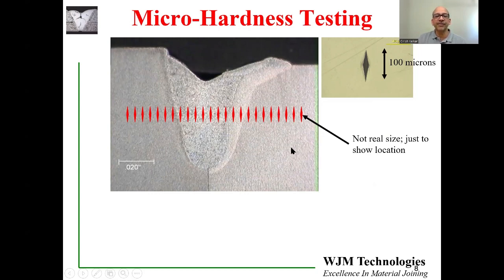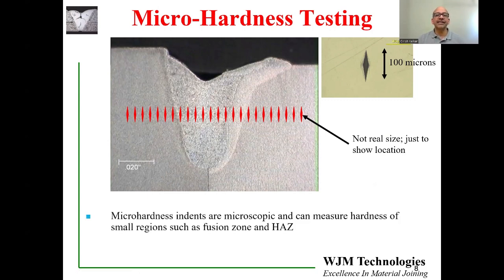So a combination of metallurgical analysis and micro-hardness testing gives a fairly complete picture of the expected behavior of the weld. There are other techniques that can be used, such as SEM and EDAX, to identify different elemental distributions in the weld, but that is not often necessary. So I would say in the majority of the cases, a good cross-section and micro-hardness testing should be sufficient for you to take the first steps in understanding welding quality.